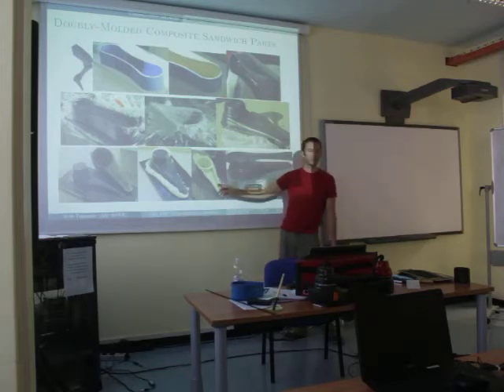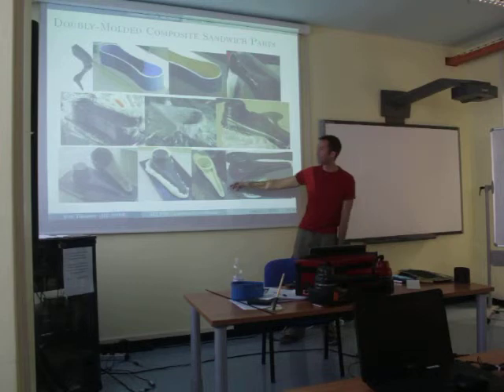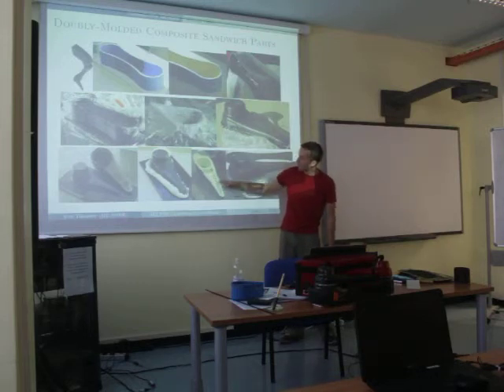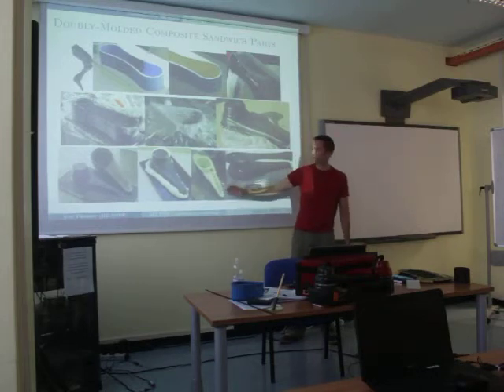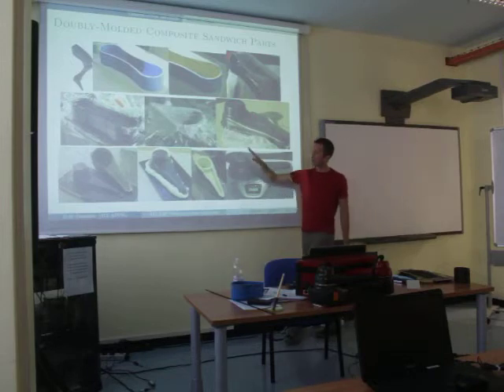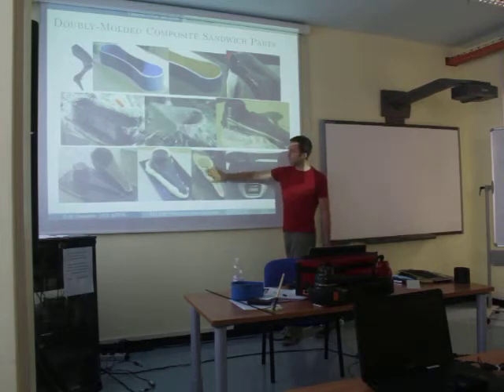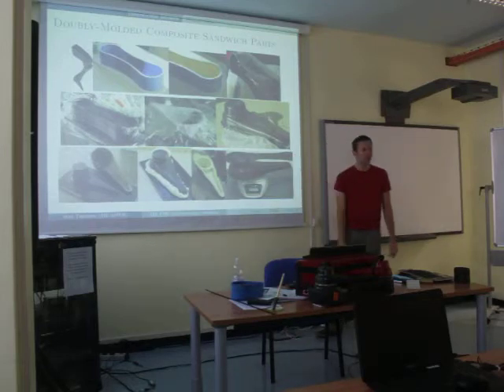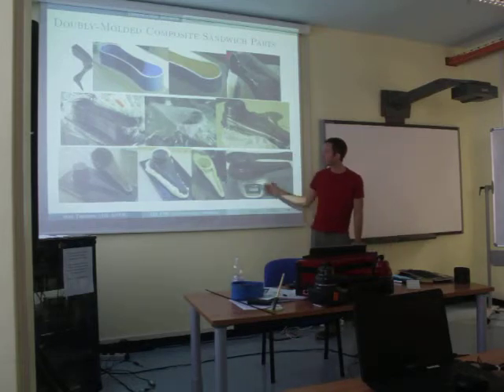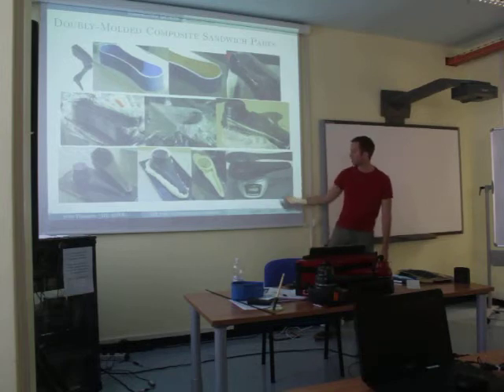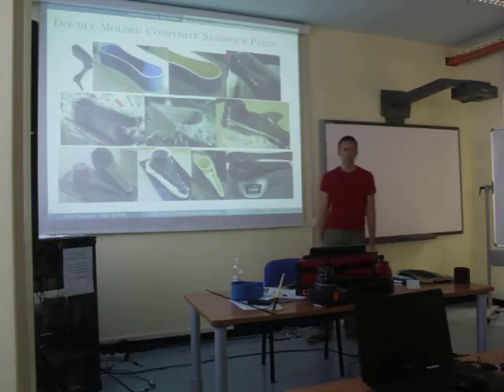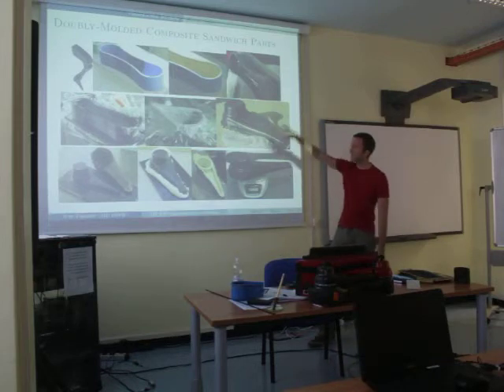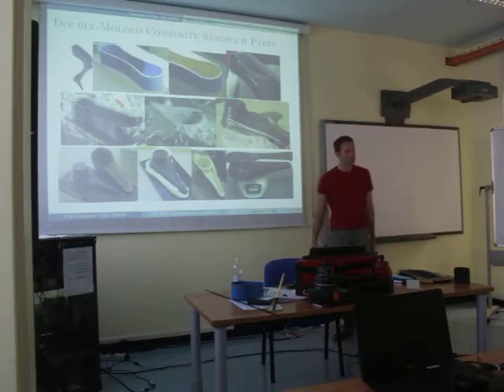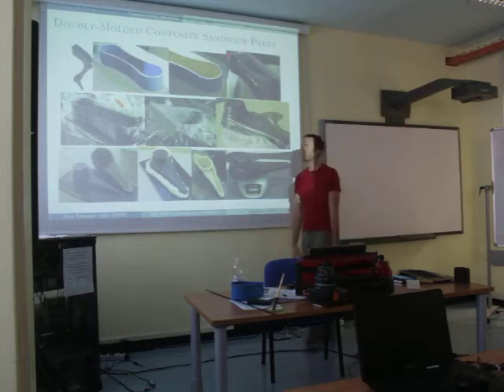If you pull that off 24 hours later or 6 hours later, however long it takes for the foam to dry, you have the inner surface of the fiberglass, and I then applied the inner surface of the part that you want, and I apply carbon fiber to that surface, and you end up with a finished part, which weighed 170 grams or something like that. So I had a really stiff, strong foot. This whole process takes a couple of weeks because each step requires that you wait a few hours.